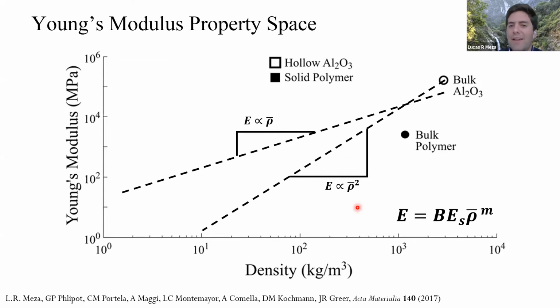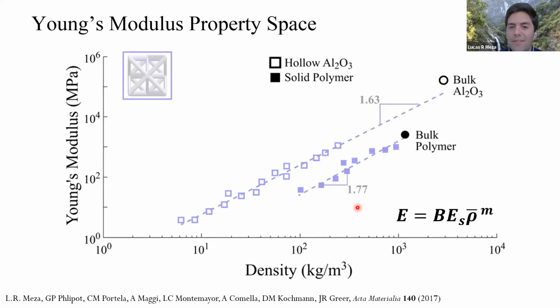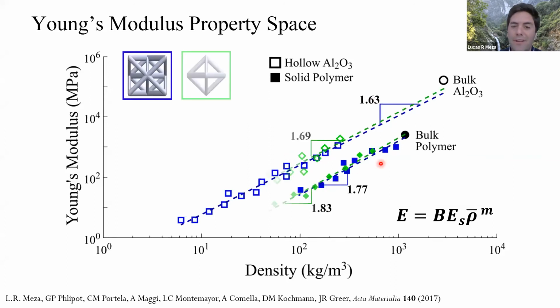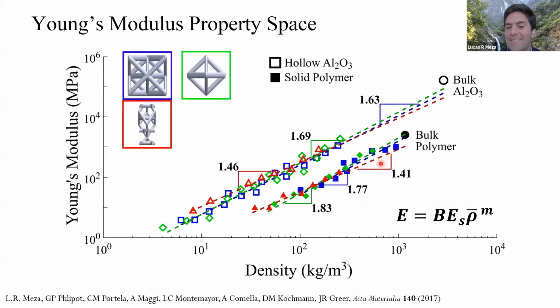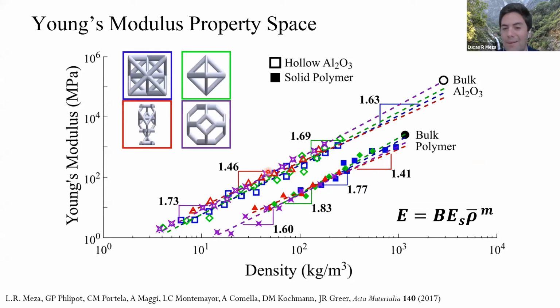We actually didn't see that behavior at all. So if we look first at the octahedron, we see it's neither 2 nor 1 scaling, both for hollow and solid beam structures. For the cube octahedron, Kagome, and tetrakaidecahedron, all of these actually collapsed onto each other very strangely. So it seemed at first glance that architecture had no role at all—that all of these different lattice architectures, even though this was supposed to be stretching, this was supposed to be bending, actually didn't make a difference, which was somewhat off-putting.